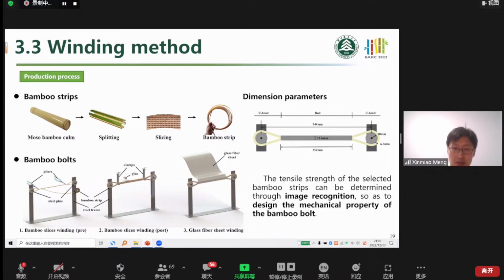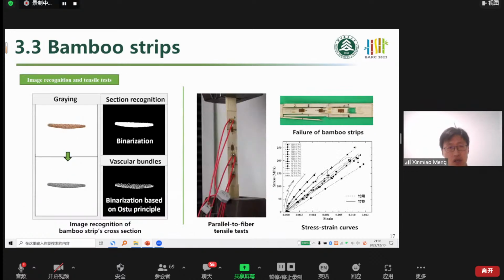And we developed a method based on image recognition to design the mechanical properties of bamboo bolts, because the tensile strength of different bamboo strips is related to the fiber of the bamboo, the density of the bamboo. And another one is that we conducted the tensile test for the bamboo strips and obtained the tensile strength. And we also defined methods to separate the bamboo strips into different groups to design the bamboo bolts based on the mechanical requirement.